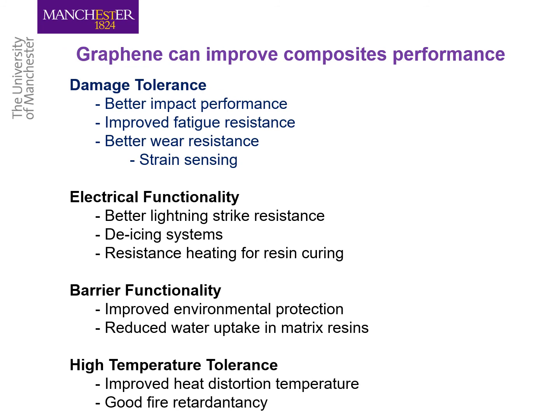So graphene can improve composite performance, can provide better impact resistance, improve the fatigue life of the composite, and can be used as a strain sensor. Electrical conductivity increases, and that can provide lightning strike protection in our structure. And the presence of graphene in the resin can reduce water uptake. Also, a small amount of graphene in the polymer composite can provide resistance to fire.